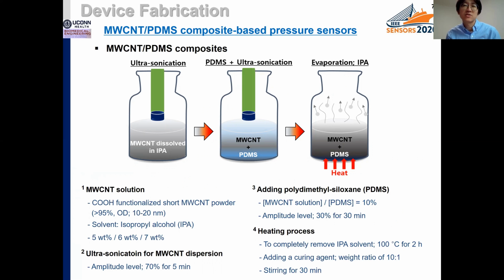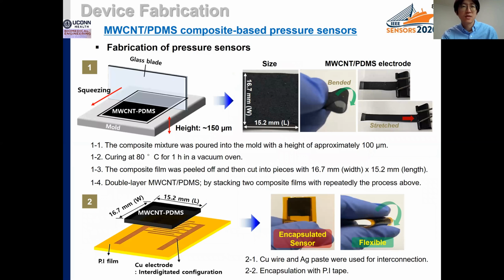curing agent was added into the MWCNT PDMS mixtures. This slide shows the fabrication process of the pressure sensor. After preparing the composite mixtures, the mixture was poured into a mold with a height of around 150 micrometers. After curing in a vacuum oven, the composite film was peeled off from the mold and then cut into pieces of appropriate size. So finally, the composite films show flexibility and stretchability.